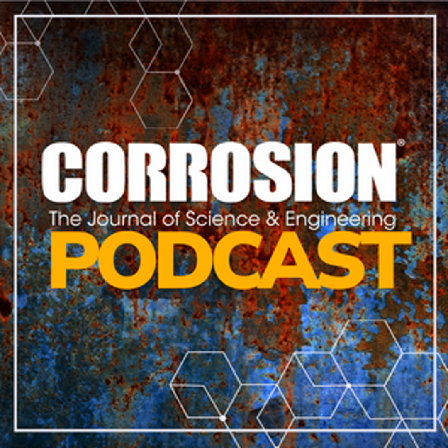For this, I think it's the first time we use ToF-SIMS, a really powerful surface analysis technique, to study the iron dissolution mechanism on carbon steel. And also the 3D images are a really powerful technique which was first used to study this kind of mechanism. And we really see the parallel mechanisms, reactions, that we see the iron hydroxide formation and iron chloride intermediate formation during this process by the 3D images. And I think other researchers can also try to use this powerful technique to study CO2 corrosion on carbon steel, on other subjects. Yeah, I think this opens a door for other researchers on how to use this powerful surface technique to study some mechanisms of carbon steel CO2 corrosion.